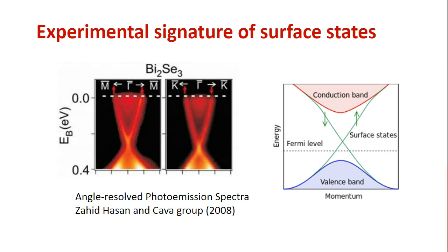You can see these lines on the left-hand side of the image, and that really conforms to these cartoon straight lines that I was talking about, which are the signature of the surface states. So this is the experimental proof. This technique is called ARPES. Using this ARPES method, it was proven that indeed we have a signature of topological materials: measure these band structures, and look at the existence of surface states. And ARPES turns out to be the best method to do that. So I'm not going to go into any more details of what topological insulators are. I'm going to switch to, again, what we are interested in primarily.